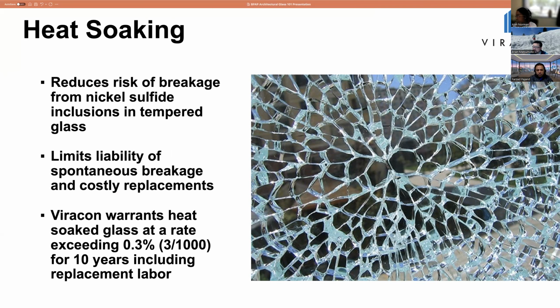So nickel sulfide has been around forever. Well, ever since they've started tempering glass and making float glass. Basically, it's an impurity, either from a batch material or something, that falls into the float tank. A float tank is, if you imagine about half of a football field that goes about 6 stories deep and has molten glass and basically flamethrowers across the top that heat that batch material and the raw glass to the point of being a liquid.